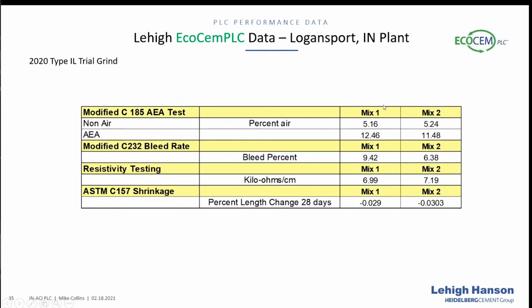What we saw, mix 1 was the July Type 1, mix 2 was the July PLC, and with no air entraining admixture, pretty much equivalent, 5.2, or 5.16 to 5.24. We did see about 1% less with the air entraining admixture, and again, that's something we've seen a few different times in the field. It's not unsuspected or unsurprising when you consider that the PLC is ground finer, and that typically requires a very small adjustment in air entrainment. Once you make that, it locks in and is steady and you don't have to worry about it anymore.